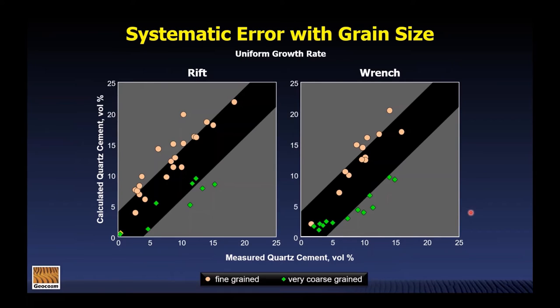Now, I'm sure some of you are already thinking about hypotheses that could explain this, and one of the ones that came to us right away and might have come to you is that maybe the silica supply assumption is wrong. Perhaps because these fine grain rocks have lower permeabilities, we weren't able to supply silica as rapidly as we could, for instance, to these very coarse grain rocks. And that's certainly a very valid hypothesis to test. However, we had some other lines of evidence to suggest that actually what might be going on is that the rate of growth per unit surface area, for some reason, is slower in these finer grain rocks compared to these very coarse grain rocks. And so we set up a laboratory experiment to test that hypothesis.